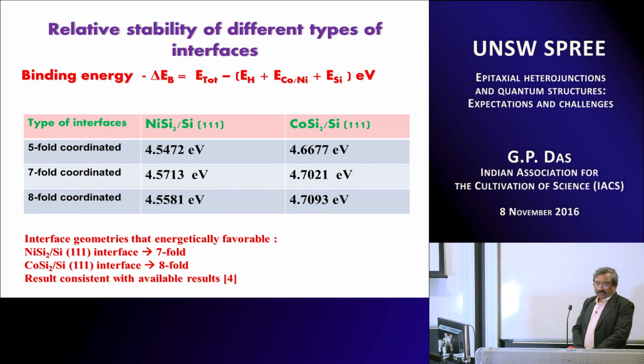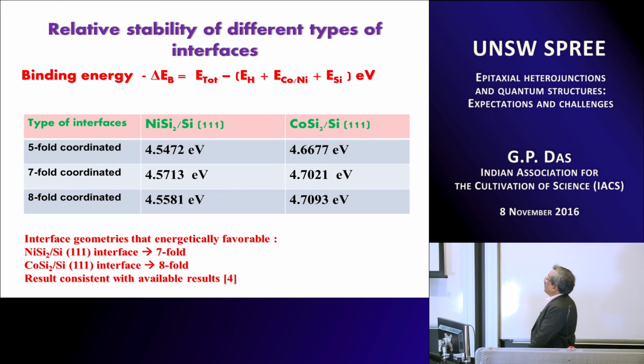Let us now look at the binding energies of the 5-fold, 7-fold, and 8-fold coordinated interfaces of the NiSi2 to Si. Look at the numbers, and it is possible for you to see which one is the most stable. For NiSi2, the most stable is the 7-fold coordinated. You can see that, this is the one. Whereas for cobalt disilicide, it is the 8-fold coordinated which is the most stable. And these results are consistent with the literature.